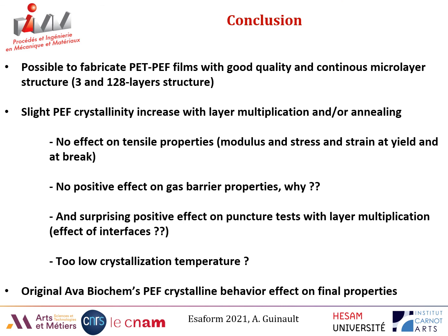So to conclude, it's possible to fabricate PET-PEF film with good quality and a continuous microlayer structure. We have a slight PEF crystallinity increase with layer multiplication and annealing, but we don't have an effect on tensile properties. That is very good. But unfortunately, we don't have also a positive effect on gas barrier properties, and it is interesting to understand. And surprisingly, we have a positive effect on puncture tests with layer multiplication, as we have said. And perhaps it is an effect of interfaces.